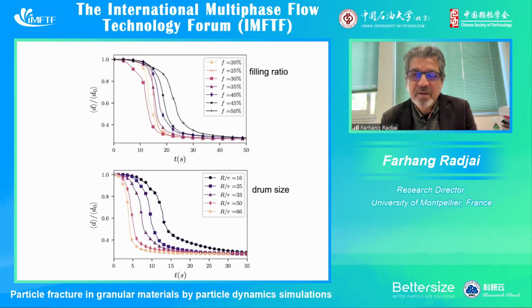We changed different quantities which are important for grinding. Filling ratio, for example, this is the height of the material inside the rotating drum. The drum size as compared to the particle size. So we went here in this example from 16 to 66. And we see that it's not only the Froude number which is important. We have also these quantities which control the breakage.